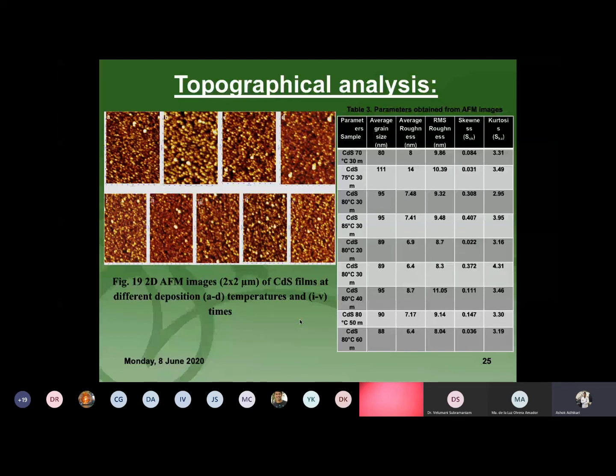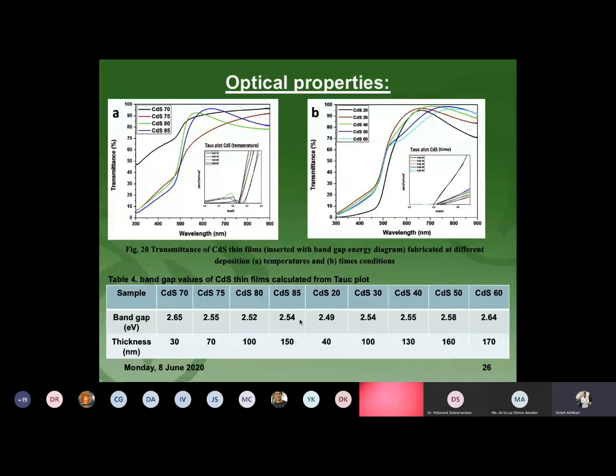For the optical properties, we analyzed using UV-Vis spectrophotometry, and calculated the transmittance values of the films from the graph. For both cases, more than 80% transmittance was observed in the visible region.